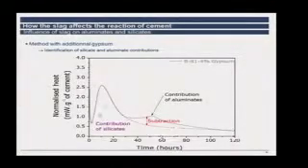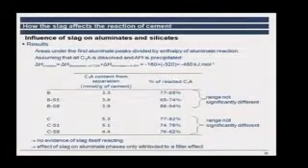So we then did a much more detailed study. We did a kind of deconvolution of these curves to subtract the contribution of the aluminates from the contribution of the silicates. And when we did this, we saw that the amount of C3A reaction in that second peak was roughly the same whether you had slag there or not.